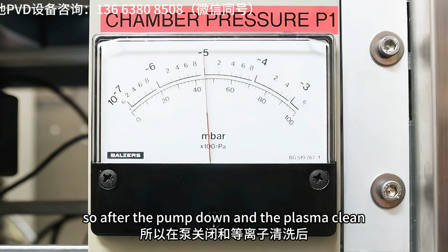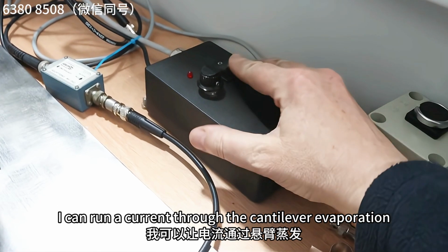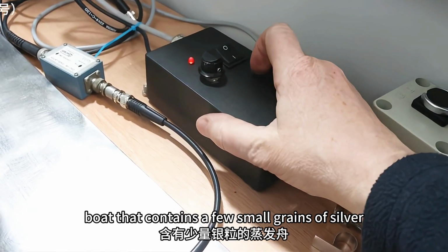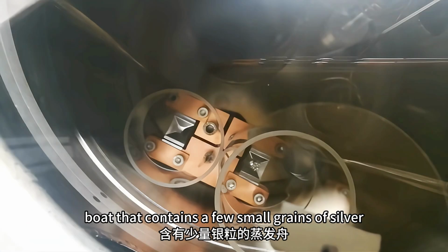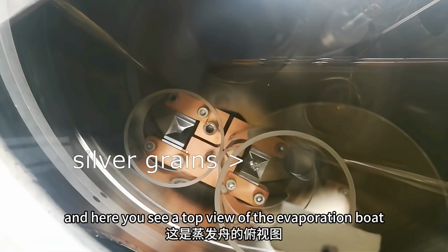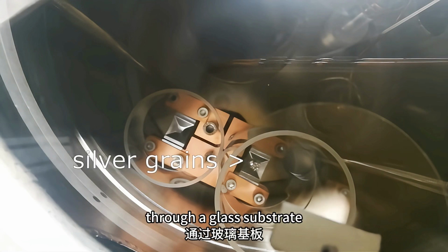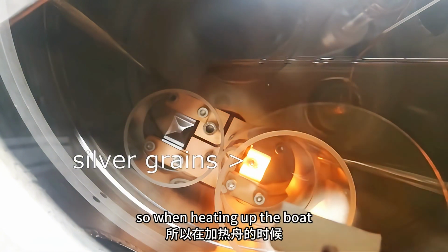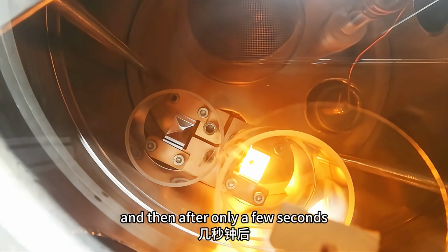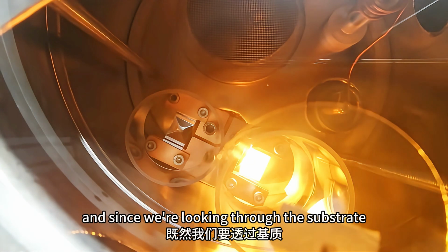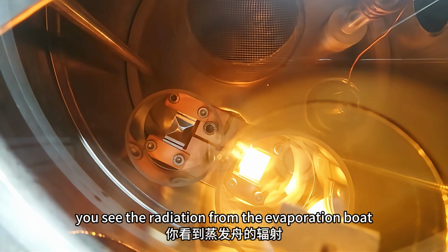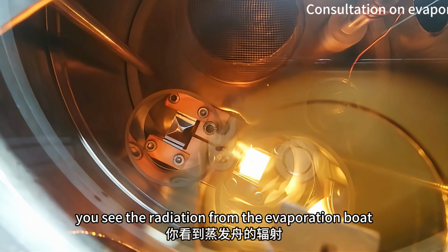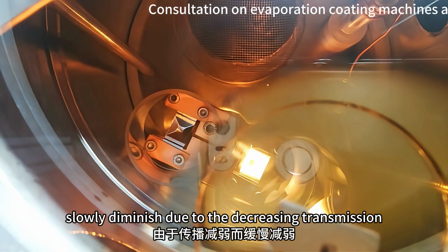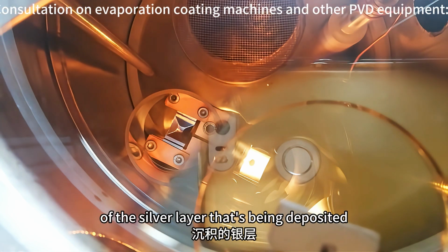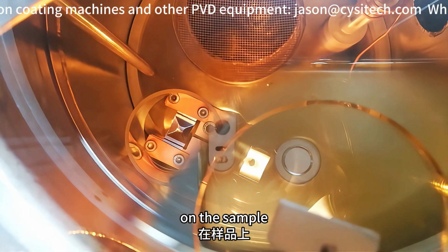So after the pump down and the plasma clean, I can run a current through the tantalum evaporation boat that contains a few small grains of silver. And here you see a top view of the evaporation boat through a glass substrate. When heating up the boat, you first see the silver melt, and then after only a few seconds it starts to evaporate. And since we're looking through the substrate, you see the radiation from the evaporation boat slowly diminish due to the decreasing transmission of the silver layer that's being deposited on the sample.